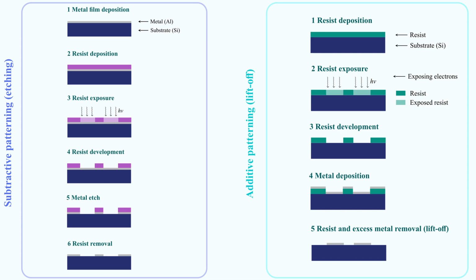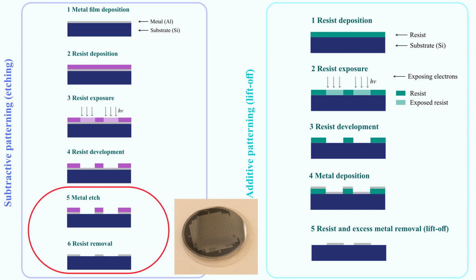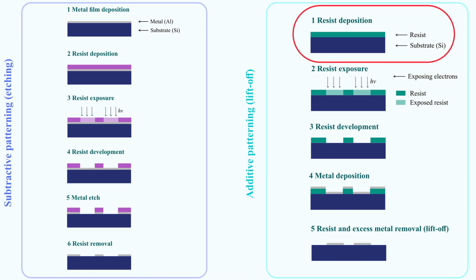So when we left the clean room the last time, we had just etched the big circuit into the metal, and I was going to get rid of the remaining photoresist. Now I'm going to spin coat the wafer with a fresh coat of resist, this time one that is sensitive to the short wavelengths of the electrons generated in our electron beam lithography system, and I will meet you at the e-beam tool.